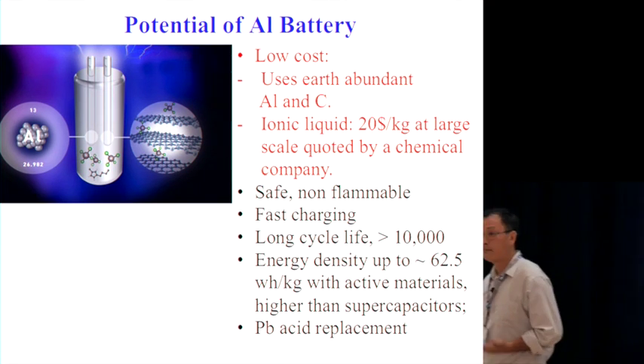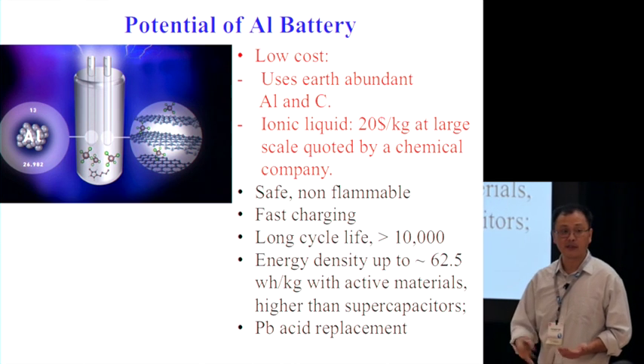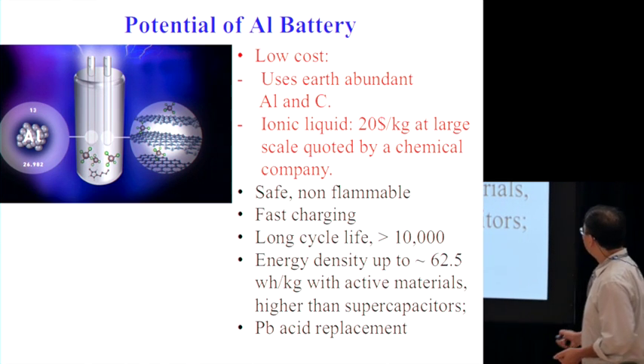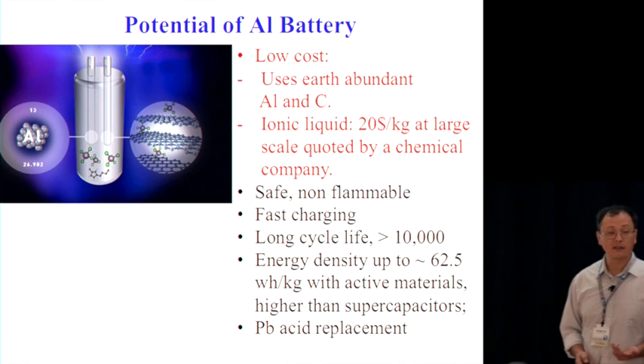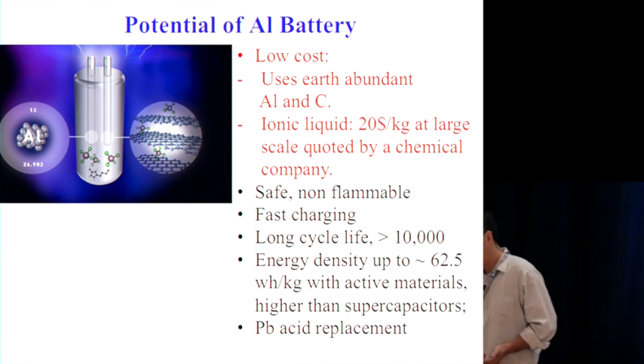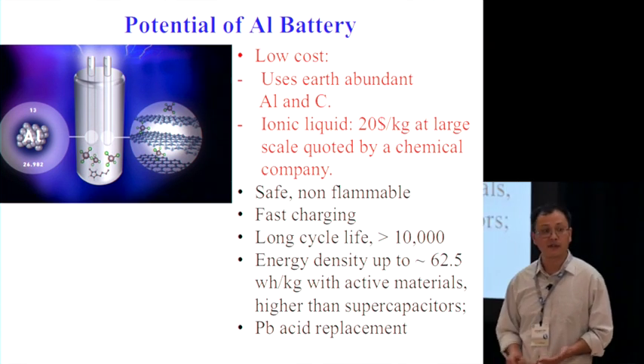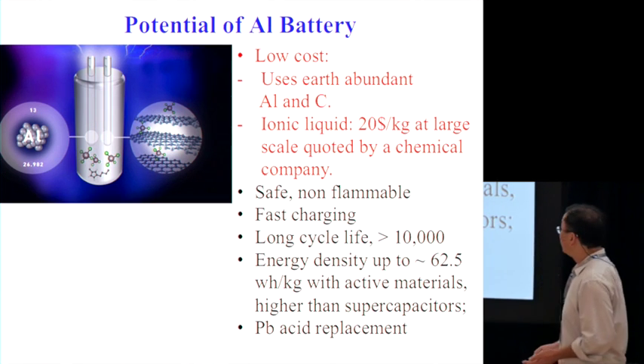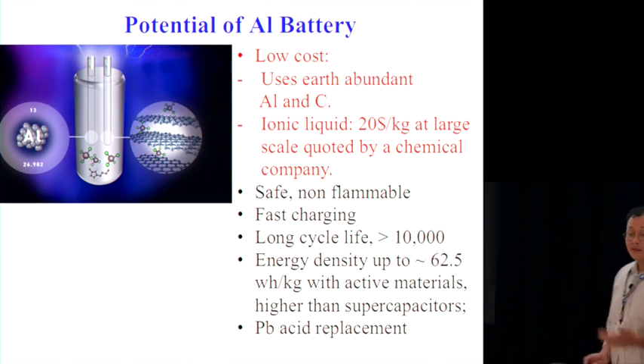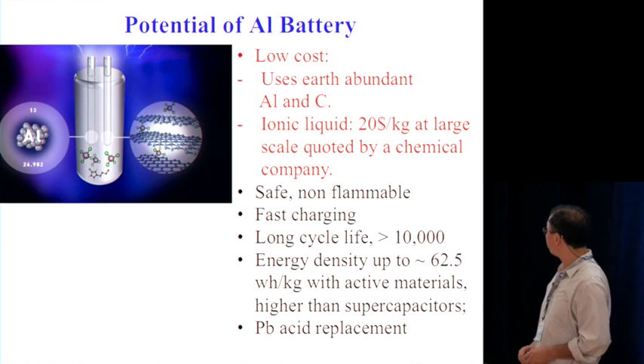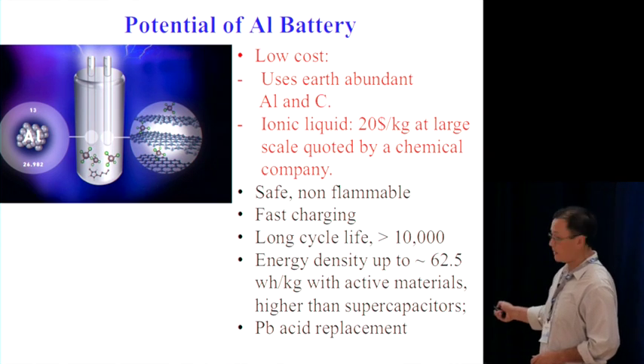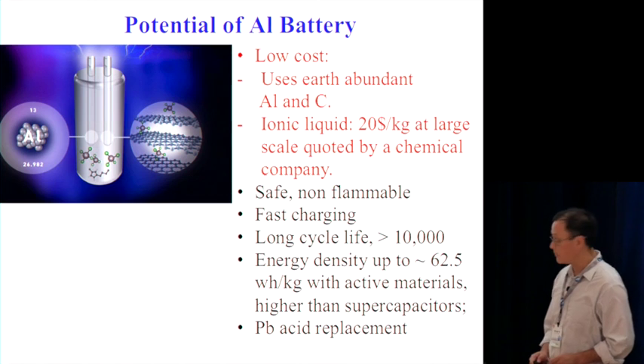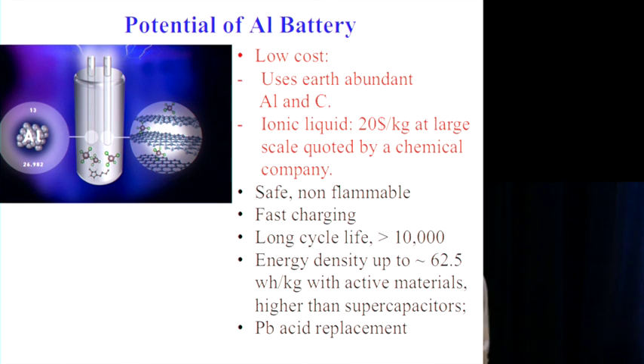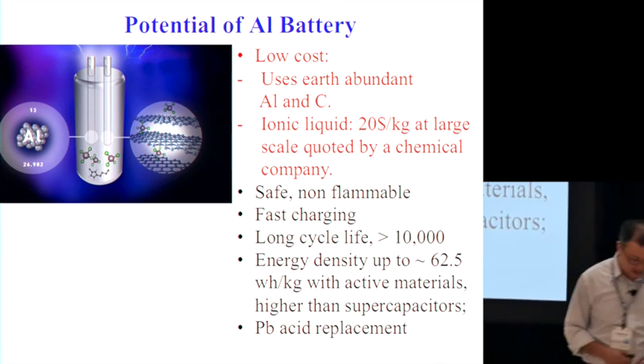It doesn't really burn as you drill through. We have videos for that. And it charges fast. You can charge in a minute, and you can discharge in 10 minutes or half an hour if you want. Okay, it cycles very well, up to 10,000 cycles. And this is the theoretical energy density, okay, 62 watt-hour per kilogram, including all these active species.